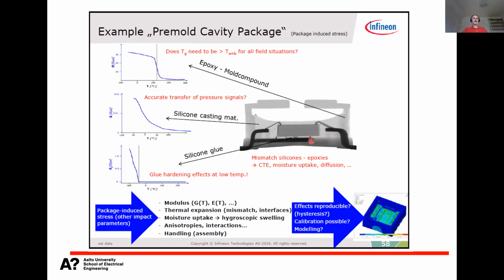So this is a pressure sensor. So here is the MEMS, and in the packaging, 3 different types of organic materials are used. So we have the epoxy molding compound. It is behaving quite the same as in the previous slide. The only difference is that now on the y-axis we don't have the CTE, we have the modulus, shear modulus, so basically the strength of the material, which is high below the Tg, and then above the Tg, the strength drops to a very, very small value. And this is how the epoxy behaves, and the Tg values are typically somewhere close to 100. It could be below 100, it could be even quite close to 200, depending on what kind of epoxies you are using.